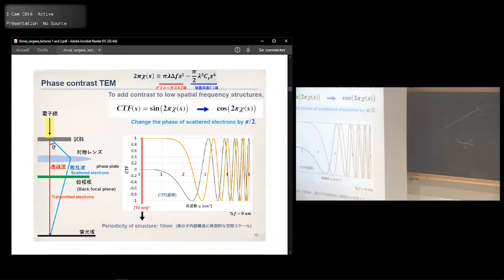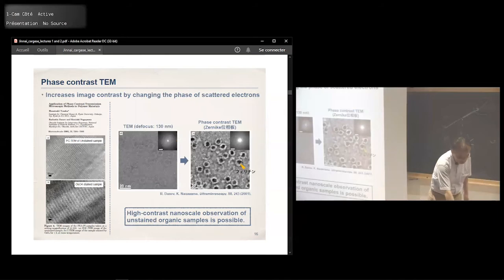Okay, so it's a very fine tuning. And then this carbon plate is easily contaminated. So you need to exchange this phase plate maybe once in 2 weeks. And you have to insert that and tune that every 2 weeks. That's a pain. So the phase contrast is very effective, but it's not so common yet.